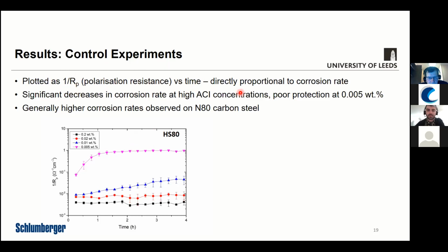For those familiar with electrochemical measurements, you'll know about measuring Tafel constants to correct the corrosion rate value you get. That becomes quite challenging in an inhibitor environment. You're not necessarily sure whether or not your Tafel constants will change throughout the experiment. So it can be quite difficult to say you have this 1 Tafel constant for the 4-hour duration and therefore a certain corrosion rate in millimeters per year. But 1 over the polarization resistance is directly proportional to corrosion rate. So when you plot 1 over RP, the trend you would see would be exactly the same as if this was shown as a corrosion rate. But we're just not introducing the uncertainty that we would get as a result of making those corrosion rate calculations and Tafel analysis.